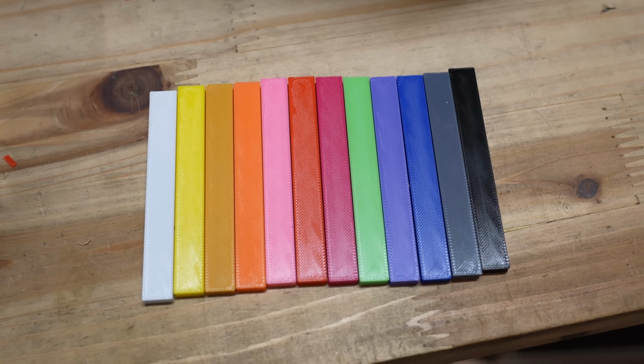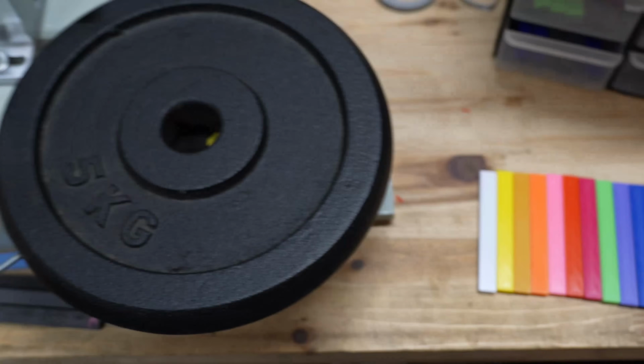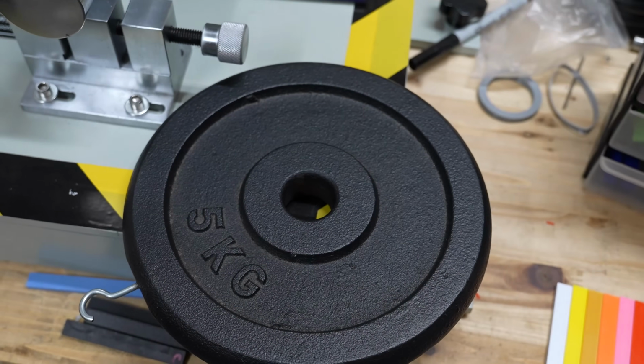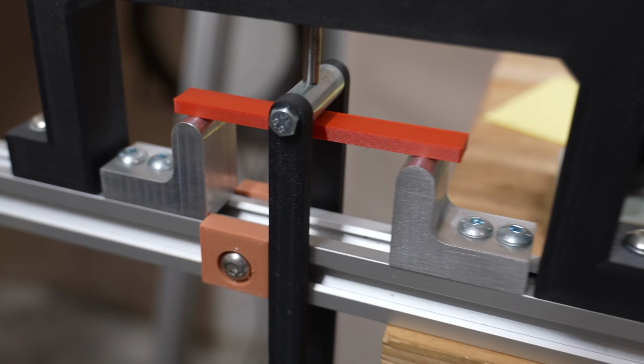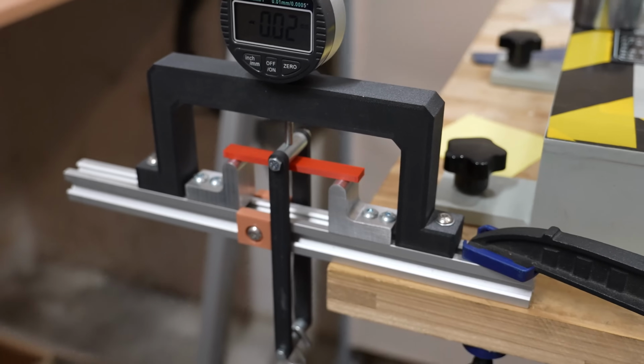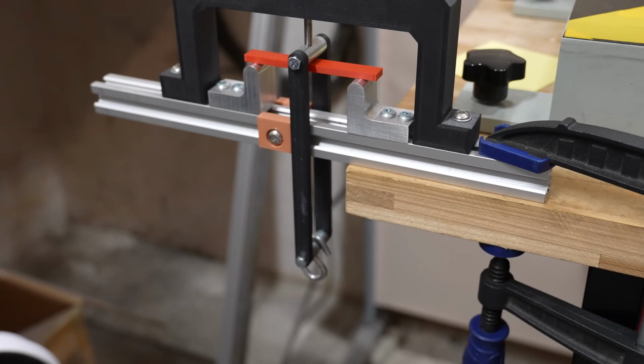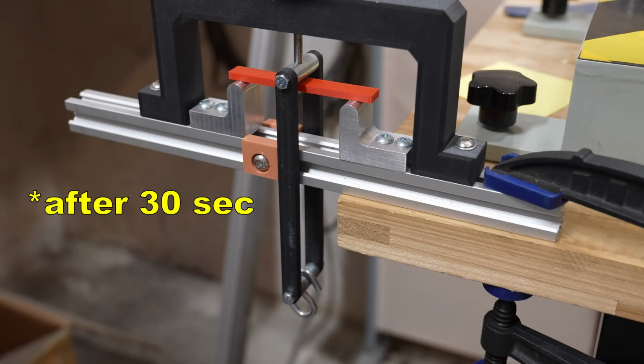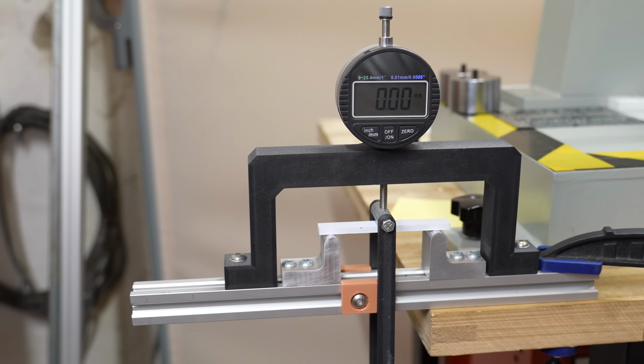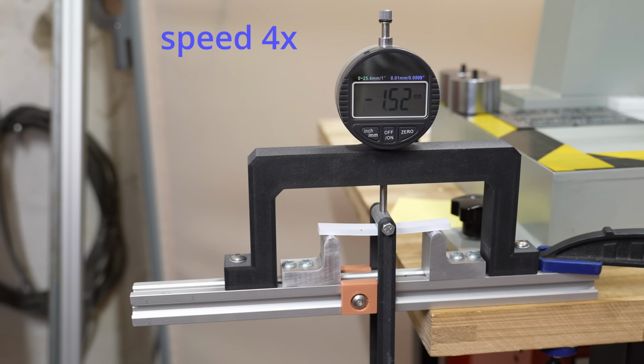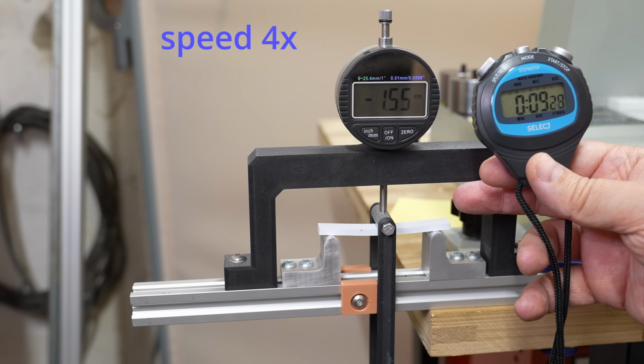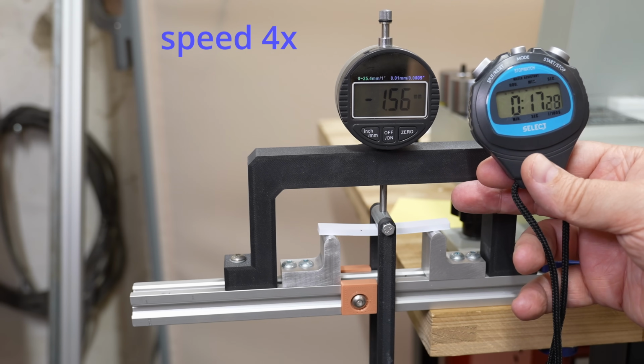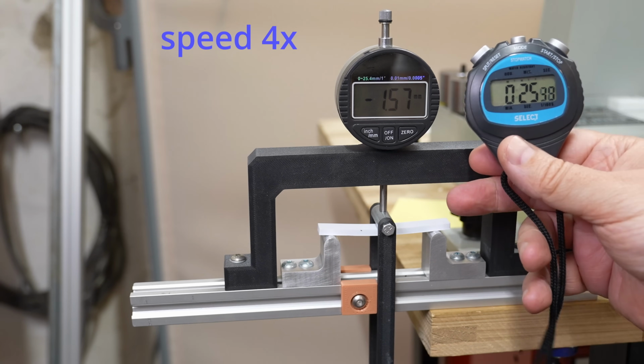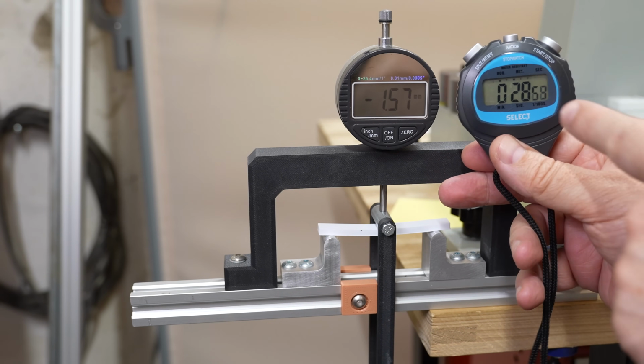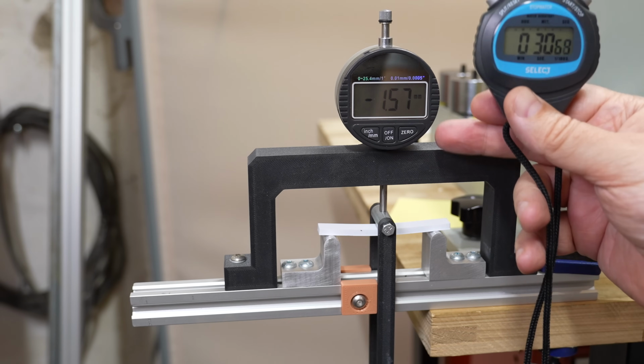And now 3-point bending test, but a simpler one. The load will be 5 kilograms. The distance between supports is 64 millimeters. And I will place the load and I will measure the deformation after 15 seconds. I'm placing the load now. This few seconds is a speed up footage. I decided to wait 30 seconds because until then the deformation stabilized.